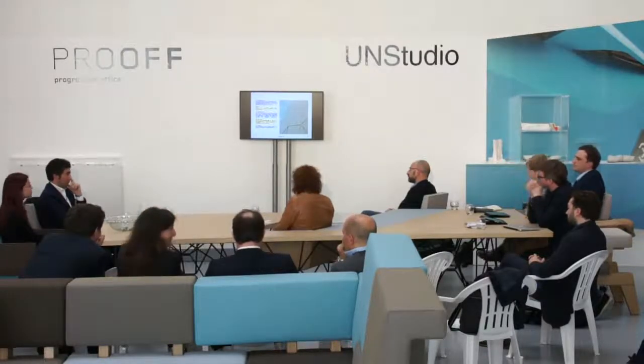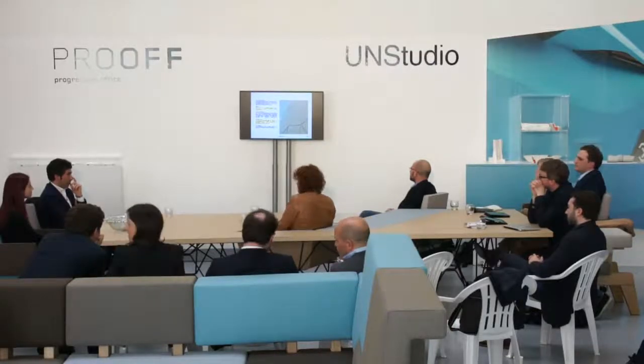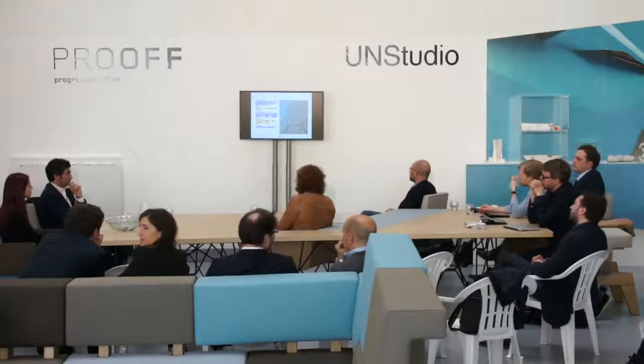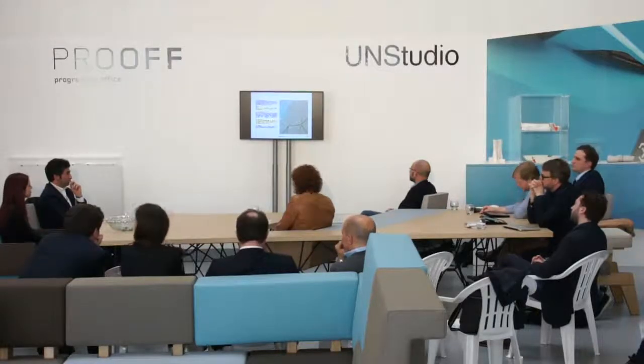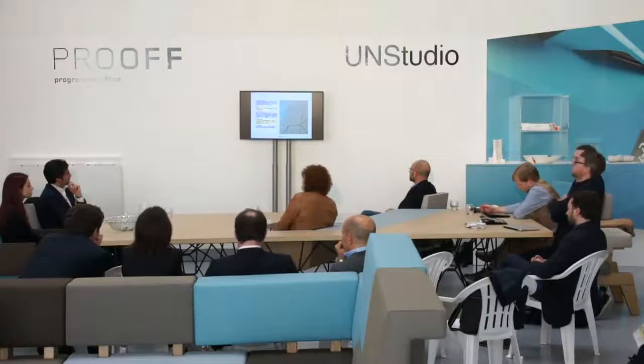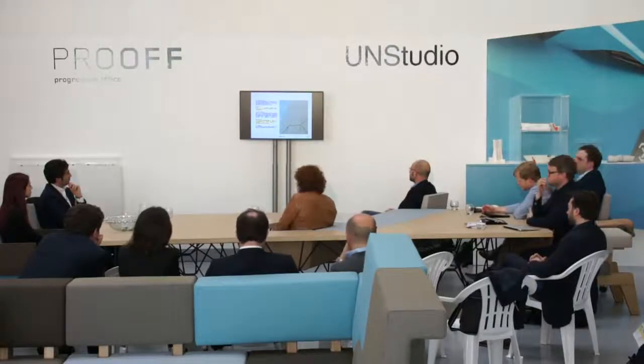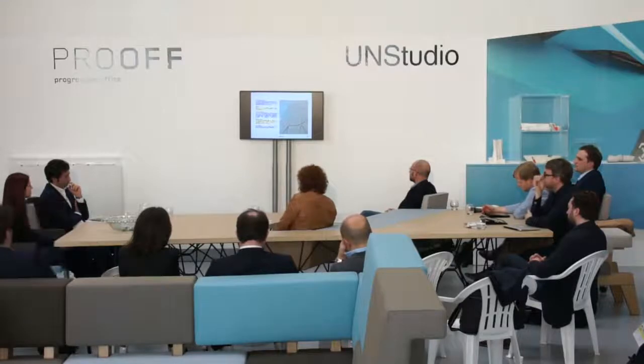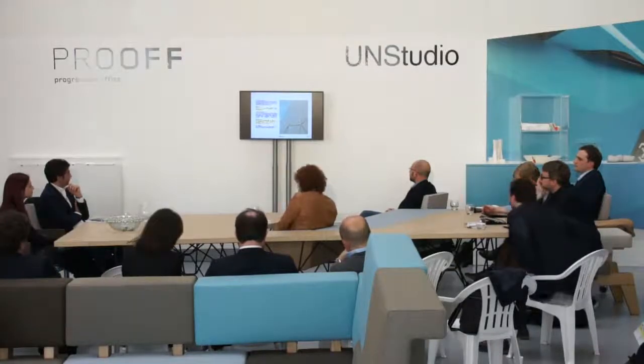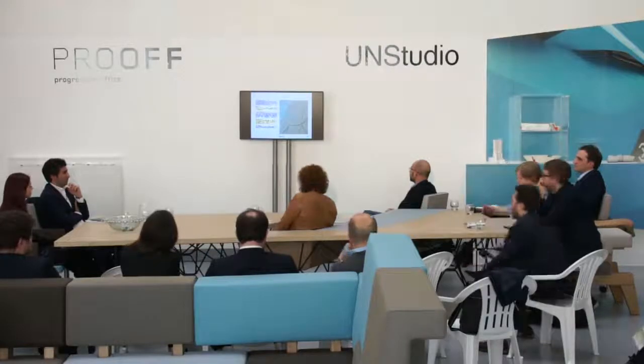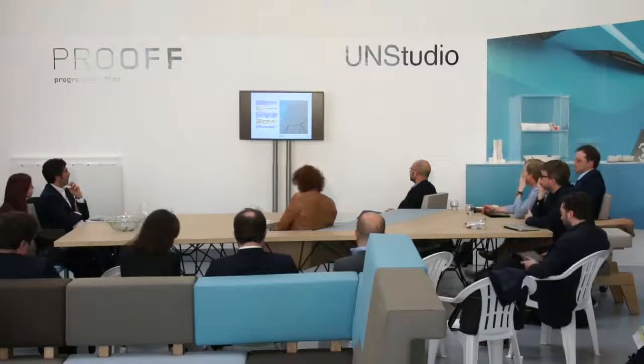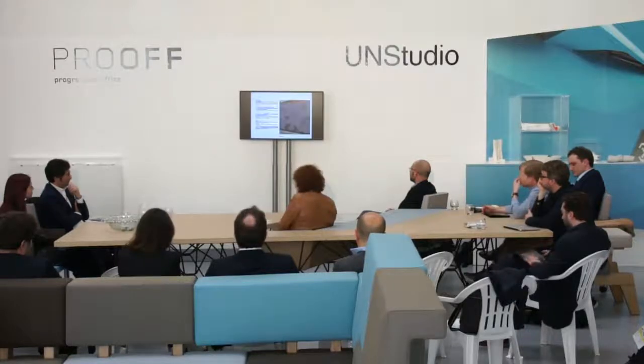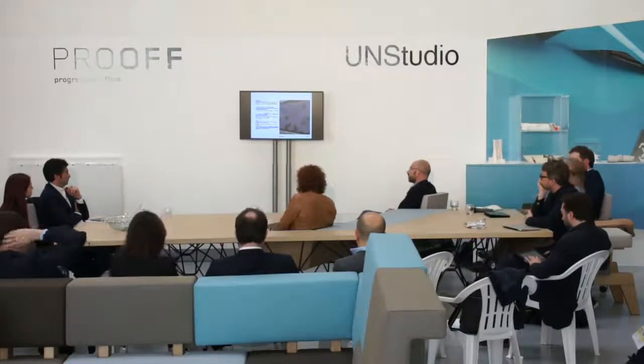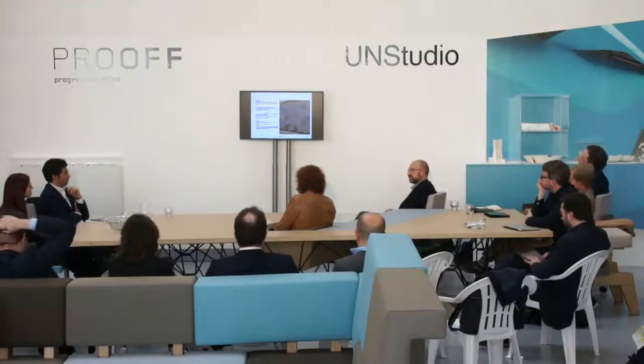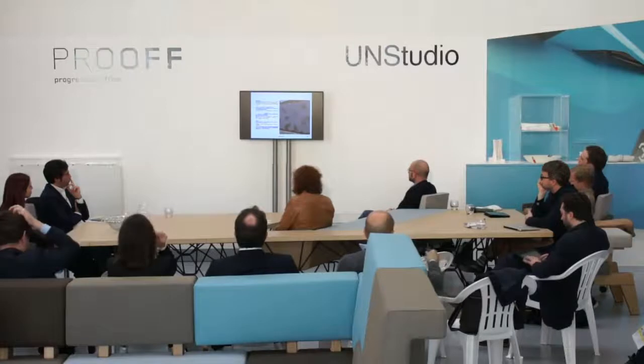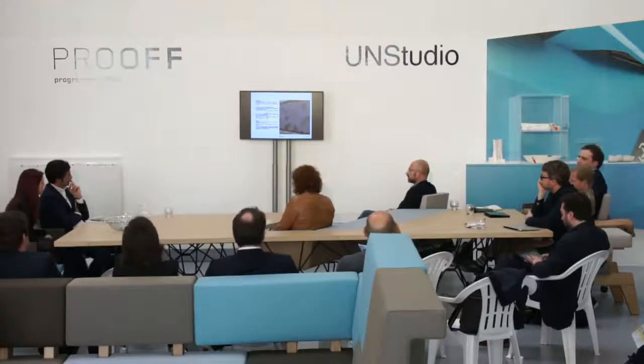Usual panels in the size of 3 meters in width up to 12 meters in length. They span unsupported 3 meters. That means you don't need any additional structures. This means also quite a cost saving for the client. And in the meantime, a lot of research has been done also to reach very high fire properties. ASTM rating class 1 is no problem anymore, which it was a few years ago. We also have a very low shrinkage, which is very important when you look into structural building envelopes. The panels come out of the mold and they basically don't change anymore.